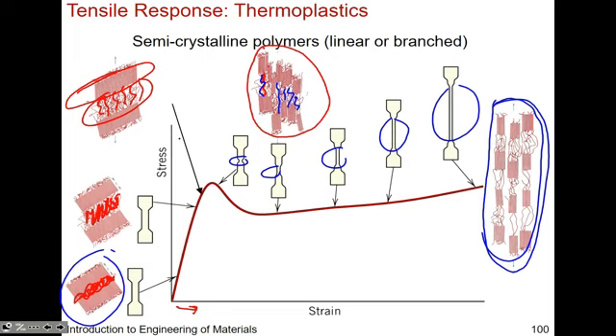Okay, and actually what happens right at fracture, what really happens, this mechanism is still being studied today on a material that is quite mature, which is polyethylene. One of the reasons why is because the techniques that we have, like X-ray scattering and X-ray diffraction, to actually probe these types of mechanisms, have a certain resolution limit. And thus we can say something about what we think is happening, but of course, materials aren't perfect, and so there's still debate. Now, a healthy debate, not like, is it or is it not, but really what the nuanced mechanism is, is the debate that's still going on today, and it's a huge area of research. But this is the generally agreed upon mechanism for polymer elongation when it's under tension.